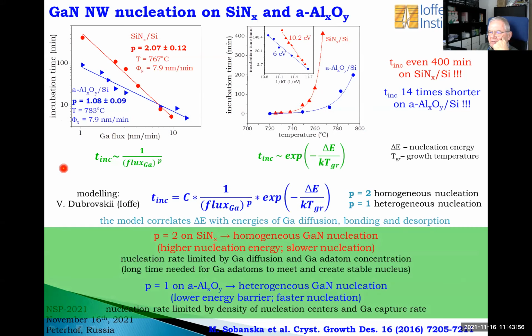And then Vladimir was kind enough to help us develop a model that correlates this power parameter P, which describes how the incubation time depends on the gallium flux, with some atomic processes on the surface, in particular with energies of gallium diffusion, bonding, and desorption. The final conclusion of this work is that if we have growth on silicon nitride, P equals 2, which corresponds in the model to a nucleation rate limited by gallium diffusion and gallium atom concentration. So this is a kind of homogeneous gallium nitride nucleation. On the contrary, for the aluminum oxide buffer, P equals 1, and this corresponds to the situation in which we have external nucleation centers.